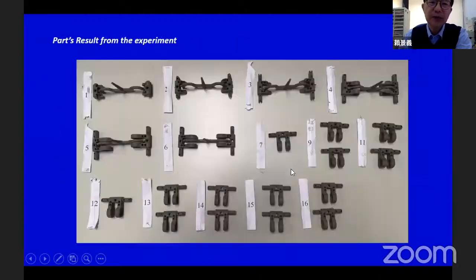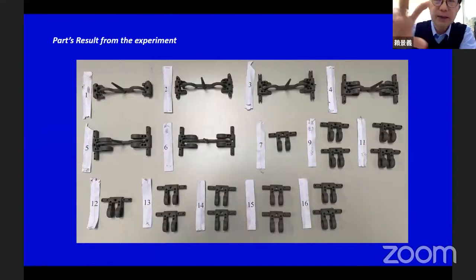But this mold just tells us that, based on this design and the verification, we can come up with a very good result. Also, we tested the highest temperature about 2 days ago. We find that if we eject the mold and measure the temperature for the traditional 2-dimensional mold and our new 3-dimensional mold, the highest temperature can be decreased about 5 to 6 degrees, which means that using our new mold, the highest temperature can be decreased a lot.